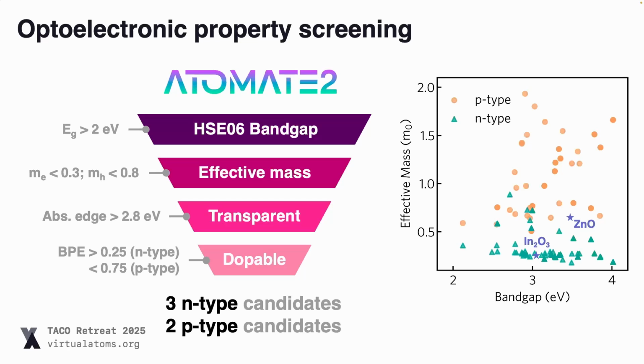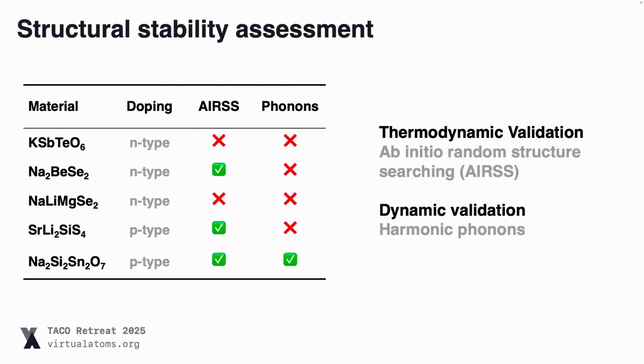The next thing we did is calculate the optical absorption, and we filtered those with an absorption edge greater than 2.8 electron volts. That's just to make sure it's going to be transparent in the range that we want. And lastly, we calculated a very, very rough metric for dopability called the branch point energy. This is just a very rough indication of whether we think it should be dopable. And actually from this screening, based primarily on the effective masses and the band gap, we went down to just 5 candidates. So 3 n-type candidates and 2 p-type candidates.